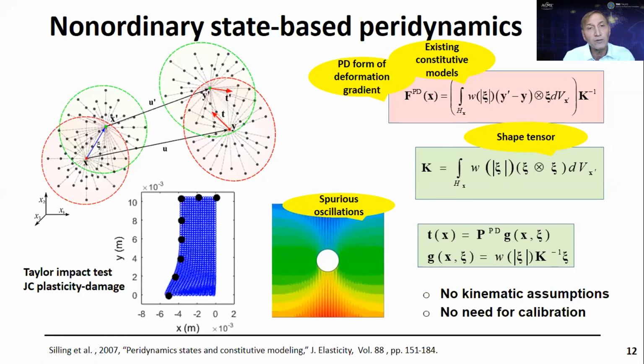And here's an example of what you can achieve with non-ordinary state-based peridynamics. Here we simulated the Taylor impact test. We have a complicated Johnson-Cook plasticity damage model. We have the strain hardening, strain rate hardening, thermal softening. We have heat due to plastic dissipation. So it's a very complex model. As you can see, it very nicely captures the experimental measurements here.